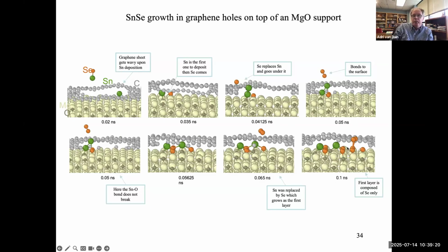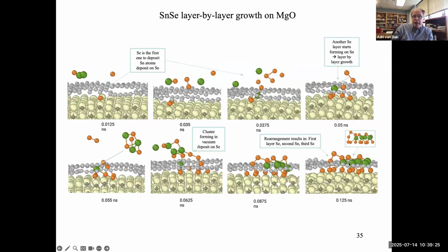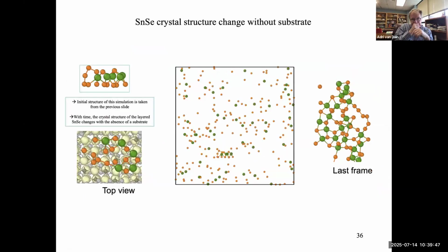The orange atoms are the selenium atoms, the green atoms are the tin atoms. In 0.1 nanosecond, we see the selenium atoms coming through. We continued it, and we actually grow a very nice pseudo-crystalline tin selenide, where the selenium likes to bind to the magnesium oxide, and we get a very nice second layer of tin. The presence of the graphene makes sure that we only grow a single crystallite. We don't grow multiple crystallites, so we get a much higher quality crystal growth.